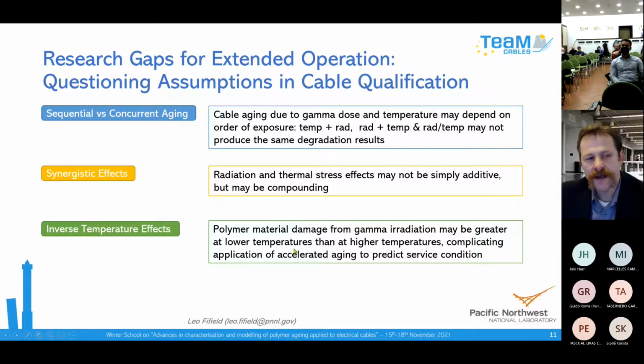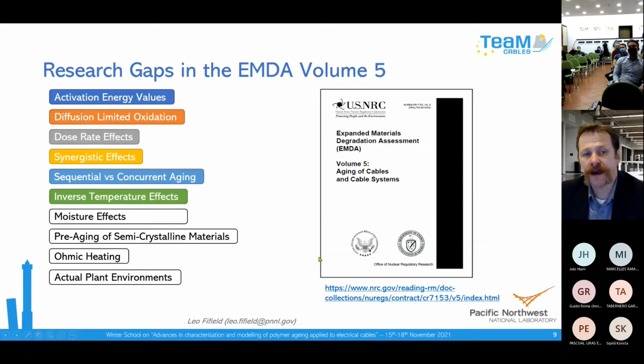And the final one is the inverse temperature effect. It's been observed in the laboratory in some cases that gamma radiation is, counterintuitively, more destructive to the polymers at lower temperatures than at higher temperatures. So normally in long-term plant operation, the temperatures would be relatively mild, and if cable polymers are exposed to gamma radiation under mild conditions, the concern is they might actually age more rapidly than when you're doing it in the laboratory at high temperature with radiation at the same time. So those are some of the knowledge gaps that the cable aging program has been addressing.